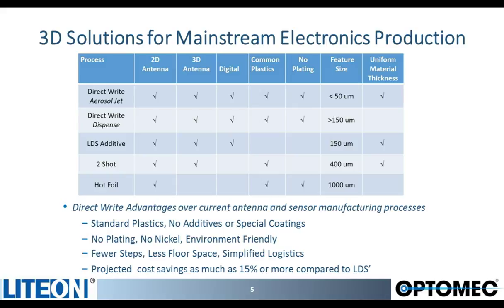Laser direct structuring typically works with doped thermoplastics delivered as an injection molded part. The thermoplastic is activated by a laser, which traces a desired electrical circuit pattern onto the molded part. And then a physical chemical reaction typically is generated by the laser interacting with the part, which forms metallic nuclei. And these nuclei act as a catalyst for reductive plating, typically copper. Now, once the part has gone through the LDS process, it is sent through an electroplating process, which typically consists of about 10 microns of copper plating followed by an overplating of 2 to 3 microns of nickel to reduce oxidation of the copper over time.